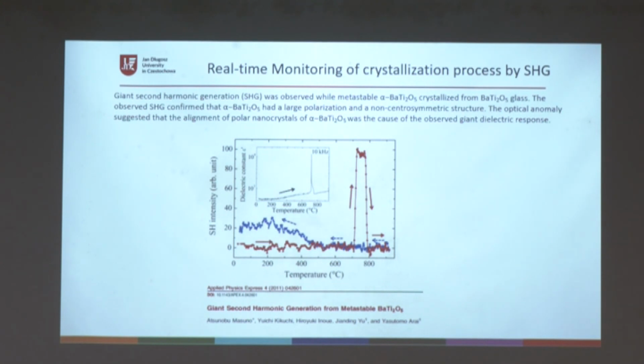And here, in practice, an experiment was done by Japanese people, who observed a crystallization process. It was interesting because they had materials in a furnace and irradiated them with a laser. When second harmonic generation appears, it shows when the crystallization process starts. It is a very good tool for investigating properties of materials during the process of preparation, as a non-contact method.